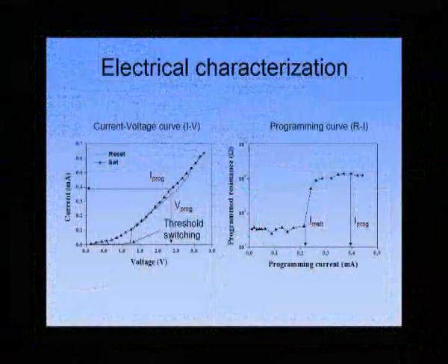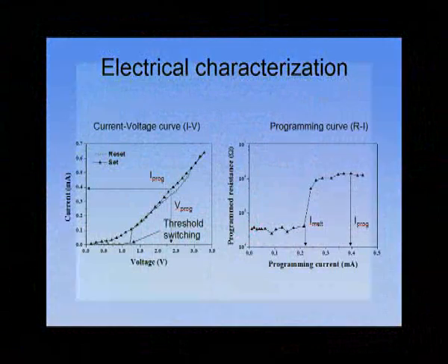Programming performances as good as those obtained using sputtered GST were reached within the project. Phase cycling was also demonstrated in alternative chalcogenide materials, opening new perspectives for device improvement. The CHEMAPH project constituted a first step toward the development of MOCVD grown chalcogenide materials for memory devices. More steps are needed to reach their development and full integration, but it's only by working in close contact between academia and industry that such an ambitious goal can finally be reached.